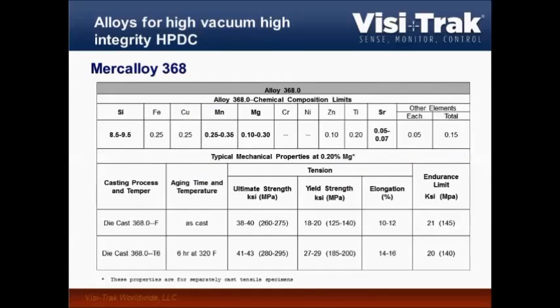If we look at the 368, so again 9% silicon, manganese same, lower magnesium, and we see higher elongation as cast, and we can boost the package even more by going into a T6. So ultimately, what you want to take away is the chemistry and the heat treatment can be tuned to meet a wide variety of property packages.